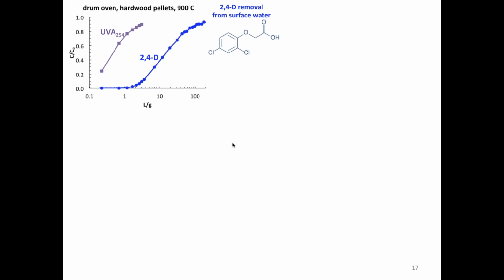One of our common test compounds is 2,4-D, which is a very common herbicide. It has some important public health, human health impacts. Also, it's an anion. It's very difficult to adsorb. It's very water soluble. So we tend to pick compounds to focus on that are really difficult to adsorb using biochar or activated carbon. Because if we can adsorb the difficult ones, then we assume that we're doing a good job controlling the ones that are removed much better by adsorption.